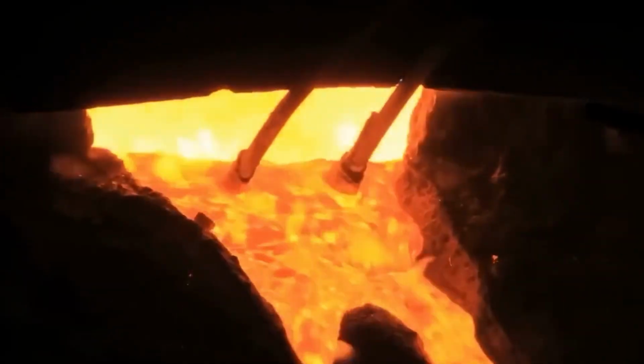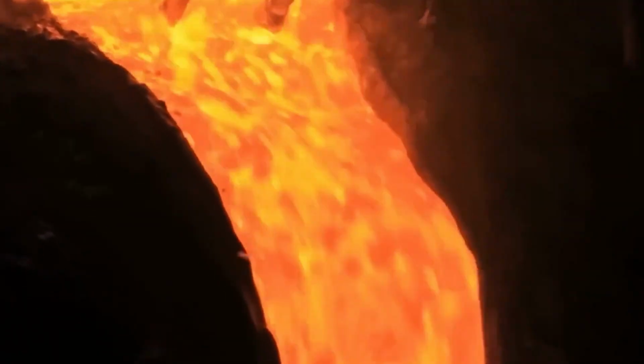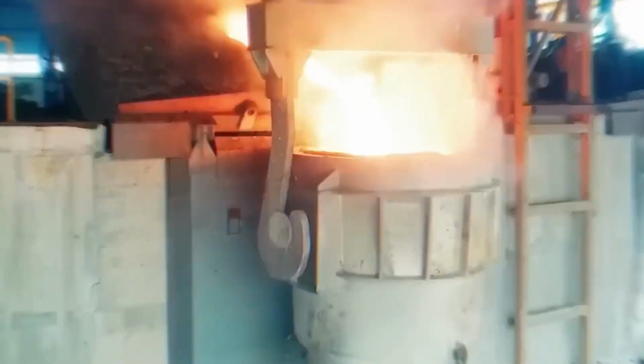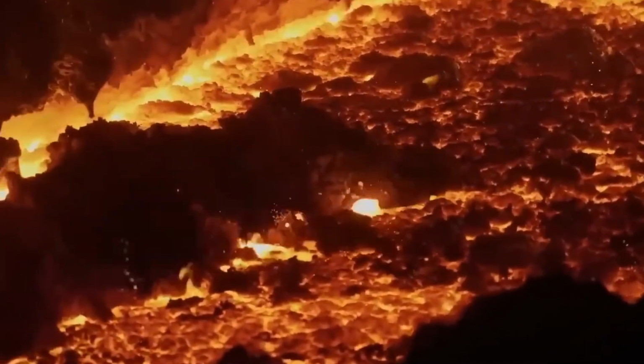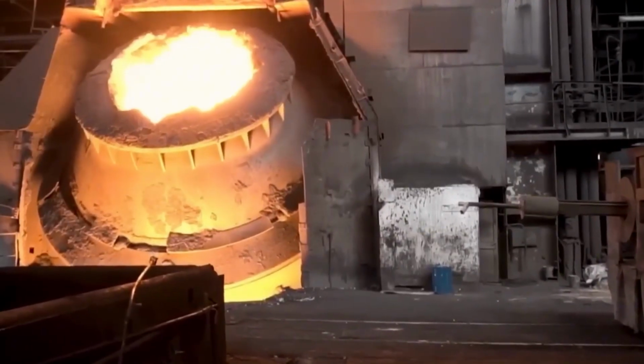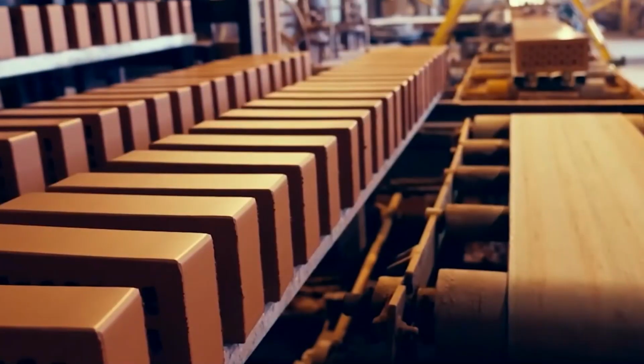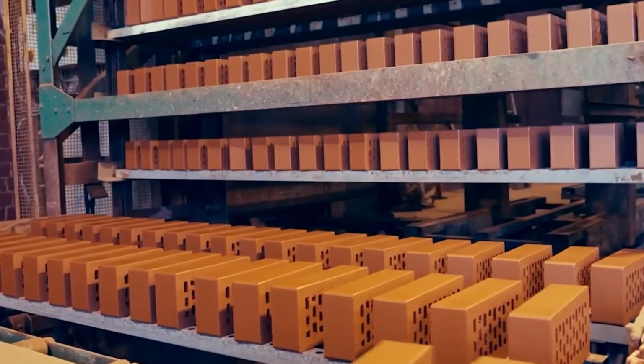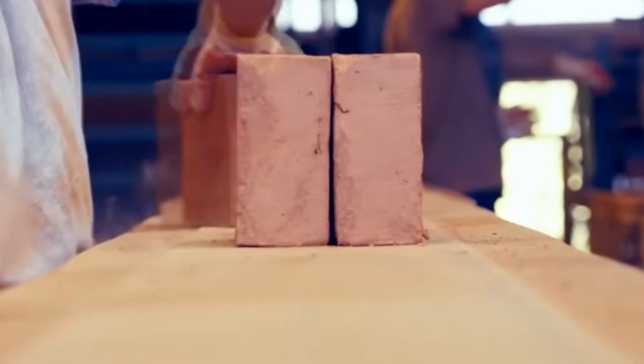The second zone is the firing zone. Here, the temperature reaches between 900 and 1,100 degrees Celsius, and the fundamental transformation of the brick takes place. At these temperatures, the minerals within the clay undergo a process called vitrification. The silica and alumina particles begin to melt very slightly at their surfaces and fuse together to form a glass-like bond between particles. The clay's plasticity is permanently destroyed. Its structure becomes rigid, dense, and durable.